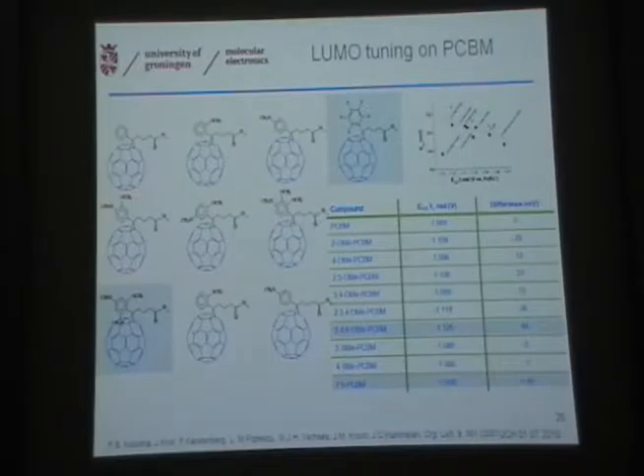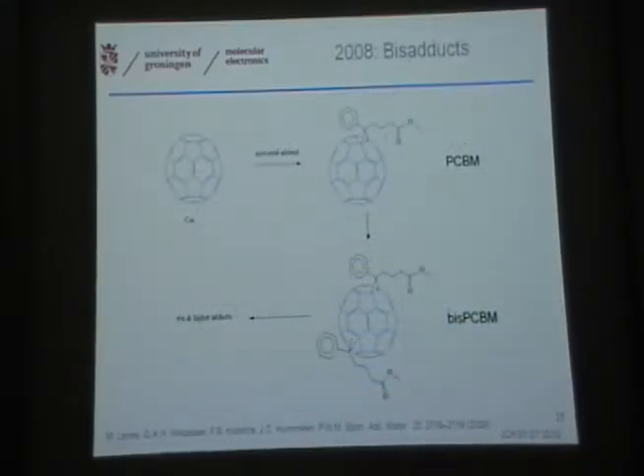It's very nice that we look at VOC trends, because it's much easier to get some good VOC from your device than to get the optimal current from your device. That's not 1 or 2 years of work, and VOC is maybe a few experiments, and you know how to do it. To get the VOC up for P3HT was really necessary, because P3HT was an improvement after the PPVs, for obvious reasons: stability, crystallinity, mobility, very nice. There's one thing that's really wrong with P3HT, and that is the position of the LUMO. So only for P3HT it was really necessary to come up with worse acceptors in order to increase that VOC. If you make the right polymer, you don't need to do that, but for P3HT we need to do